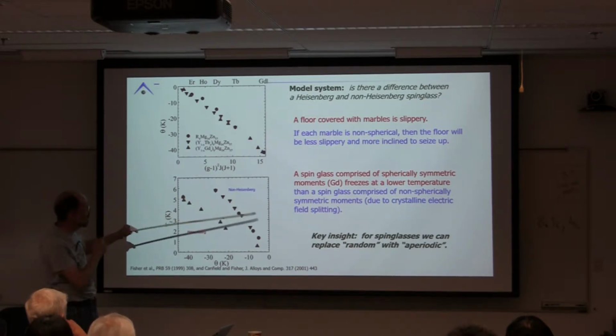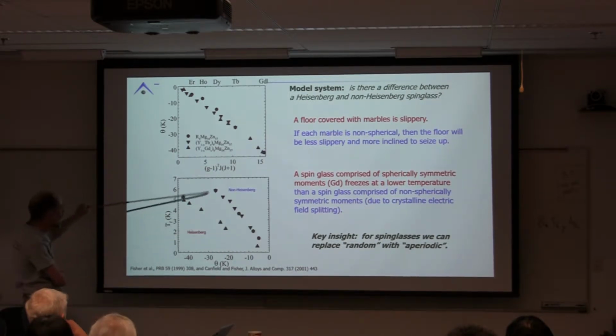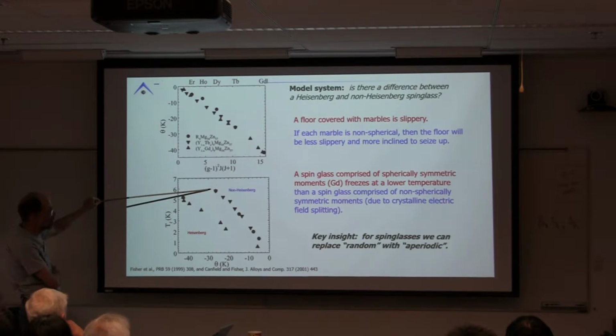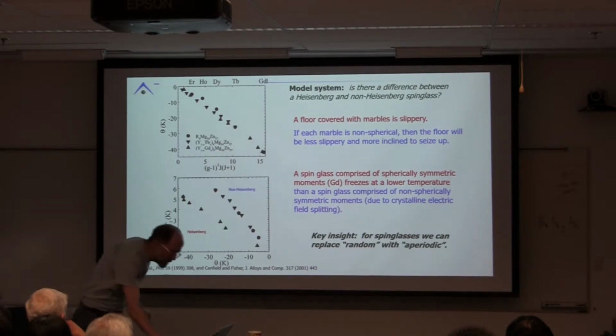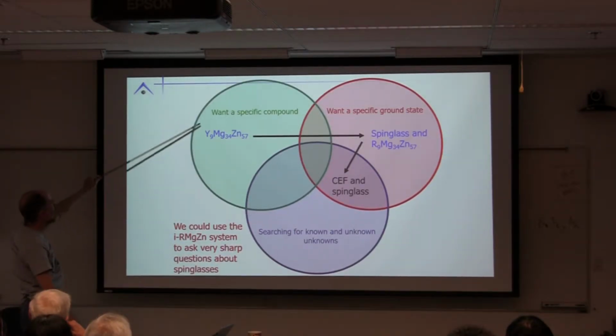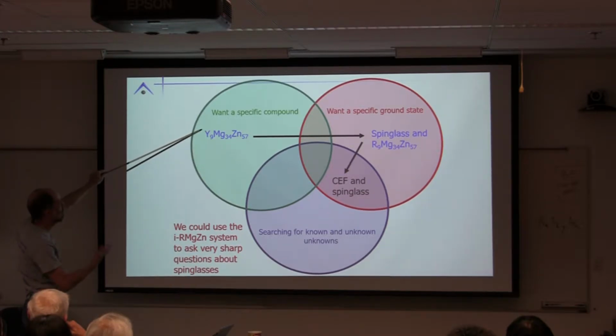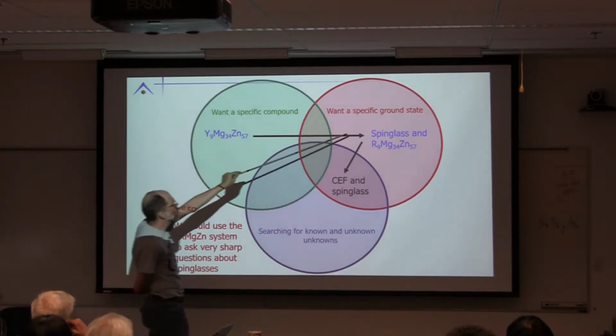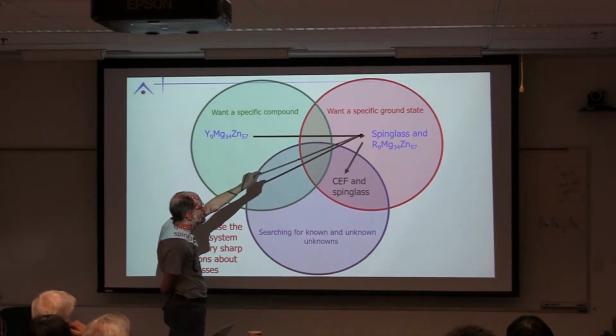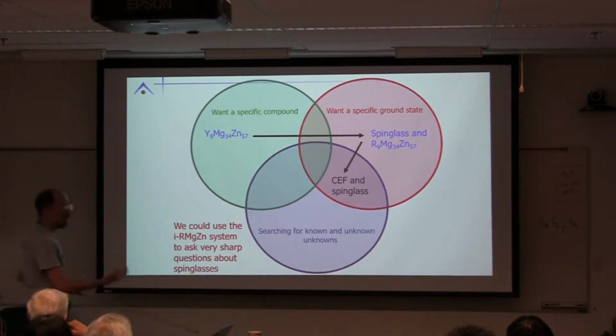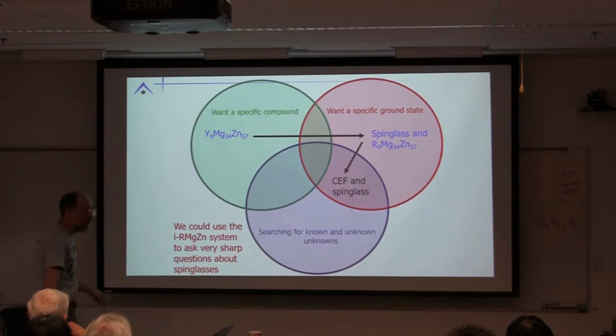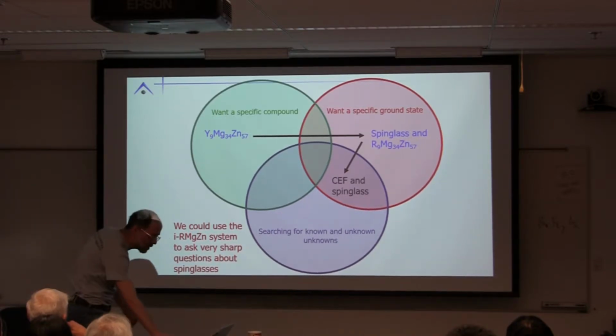If we have a spin glass, if it's a Heisenberg, a spherical symmetry, it will freeze at a lower temperature than the non-Heisenberg. Okay? So what we can see here then again is a progression from we want a specific compound, we want to see can we grow single phase yttrium magnesium zinc quasicrystal, to wanting to study a specific ground state, spin glasses, to then trying to ask questions about what we have, what are the effects of CEF splitting on the spin glass state. Okay.